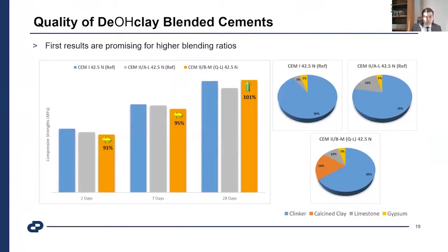When we look at the quality of the first results we achieved, we compared it with CEM I 42.5, the existing product being CEM II/A-L. The other 42.5 product, the new product, is CEM II/B-M, which includes calcined clay. As you can see here, in the early strengths it's a little bit down, but in the late strength it achieved more than CEM II/A-L and a little bit higher than CEM I 42.5. It also gives us the opportunity to check and improve it, and to increase the amount of calcined clay.